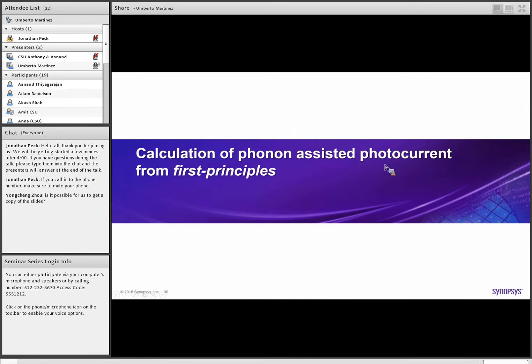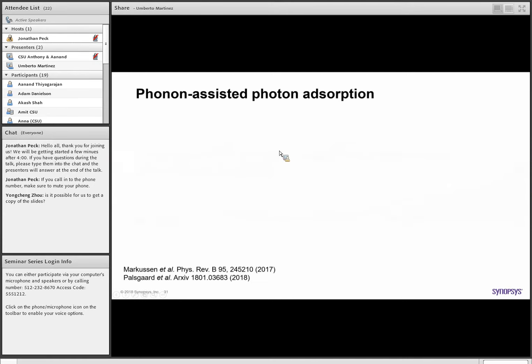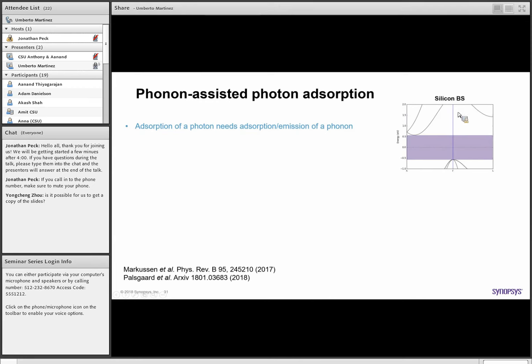Another example that I'd like to show is how we do photocurrent calculation from first principles, including electron-phonon coupling. Here I take the example of silicon again, because we all know this is an indirect band gap. So in order to have a transition from the top of the valence band to the bottom of the conduction band, the photon needs to absorb a phonon as well, and this is not a trivial problem. The theory is there, but this type of simulation, if you really want to do it from first principles, let's say with DFT, is very demanding because you need to calculate a lot of displacements and use big supercells, and that's not possible on a daily basis.